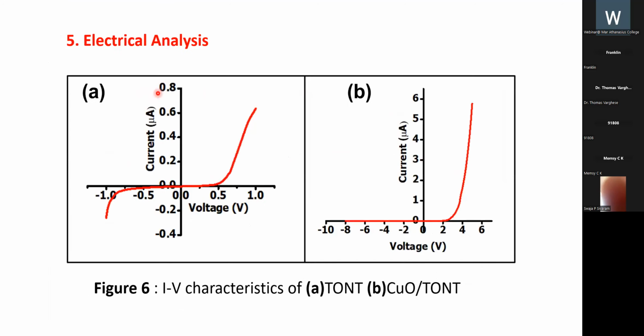The current-voltage characteristics of TONT and CuO/TONT are shown in figure 6. TONTs do not show any rectifying behavior, but CuO/TONT exhibits very good rectification. The significance of this PN heterojunction formation is in its ability to provide charge carrier separation.